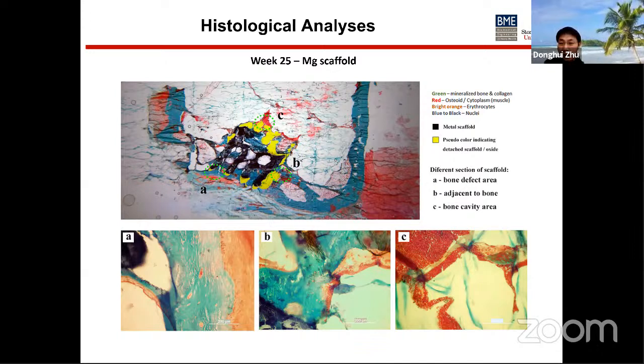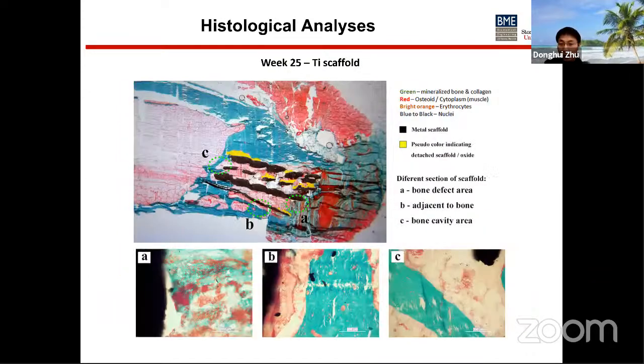At the later stage, 25 weeks for the magnesium, compared to the earlier stage, a thick mineralized bone is observed both inside and at the surrounding area of the defect. We also observed some aggregation of cells in the cavity region, as well as the bone structure inside. Those features are very obvious, and we did not observe this in the titanium implant.